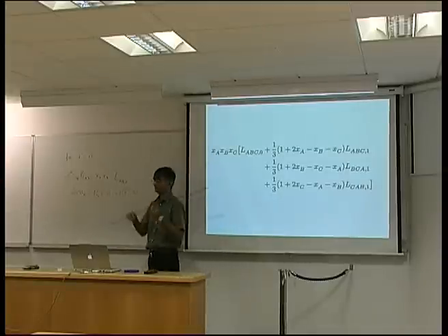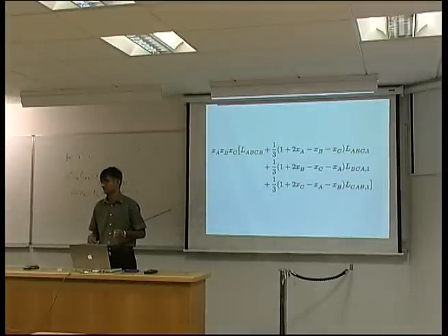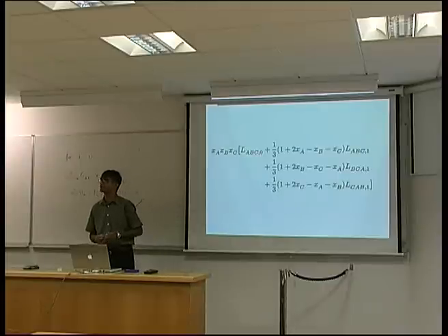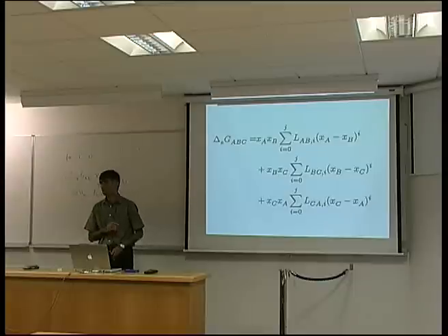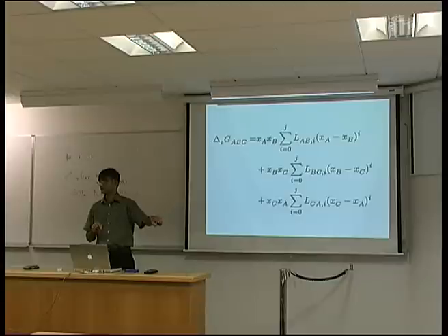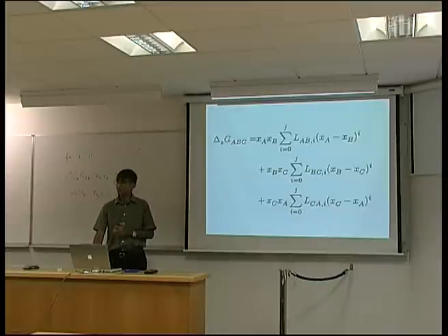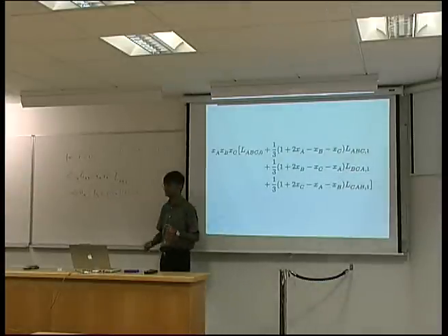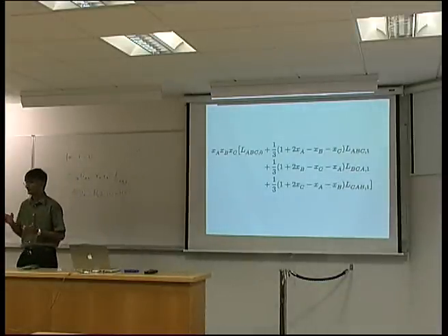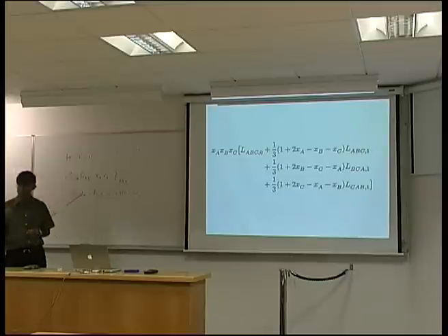So we would use a term like this where we have XA, XB and XC. So clearly this is a ternary interaction. And we have another polynomial which takes account of the different ternary interactions. Now supposing the ternary interaction is simple, then we could just use this term and not use any of those terms. But if it is more complicated, then we have to add further coefficients. But again, the equation is designed so that if I discover a new value for one of these coefficients, I don't have to go away and modify everything in the database.